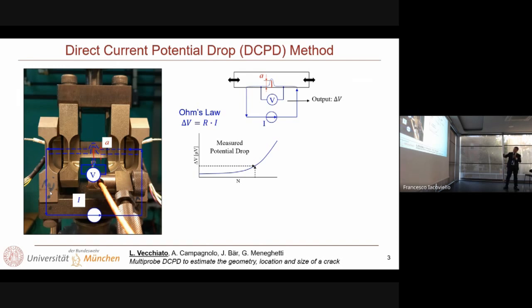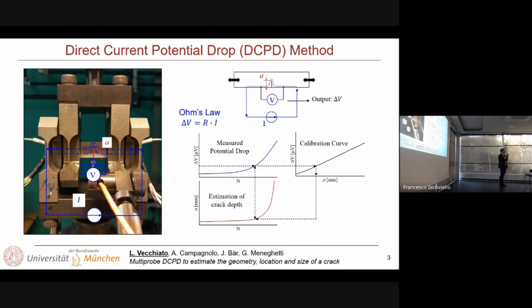And because the electrical current is kept constant, we can measure the potential drop between points of the specimen itself, and we can measure an increase of the potential drop since Ohm's law is valid. So we keep constant the electrical current, the electrical resistance increases due to an increase of the crack length, and so we measure an increase of the potential drop. Thanks to some calibration curve, we can just translate the measured potential drop into a certain crack length. And this is how the potential drop method works.